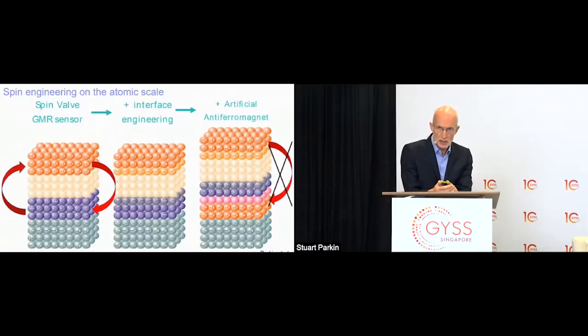Now, why is this useful? It turns out it's critically important because we can use it to design magnetic structures that would otherwise not be possible. So if we look on the left side of this cartoon, you can see a schematic of a spin valve structure. The red layer at the top is a magnetic material whose moments are pointing to the right. And then the yellow in between is copper, and the blue dots correspond to a magnetic layer with its moments pointing to the left. And underneath, we use an antiferromagnetic material to set the state of that blue layer moment so that it is unresponsive to external magnetic fields. I don't want to discuss that. It's a property called exchange bias. And this, again, is a property that I proposed we use to build this spin valve sensing device.